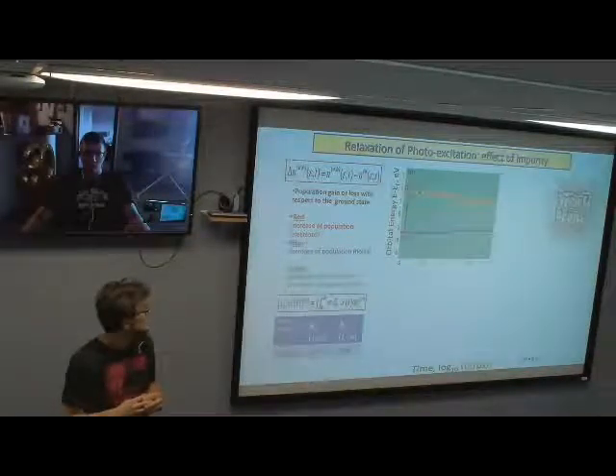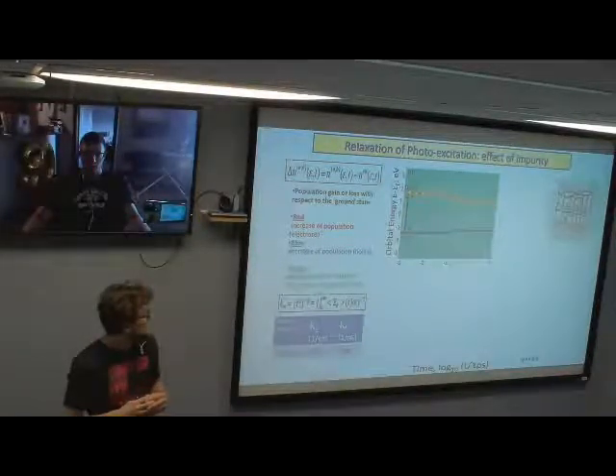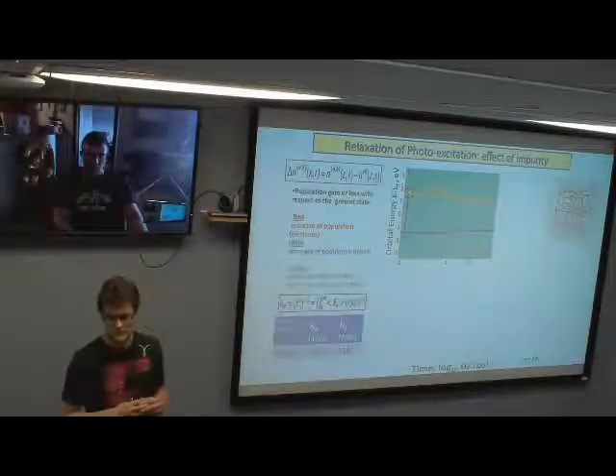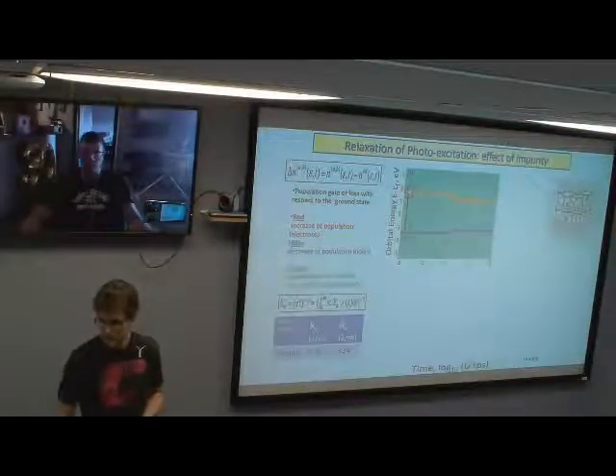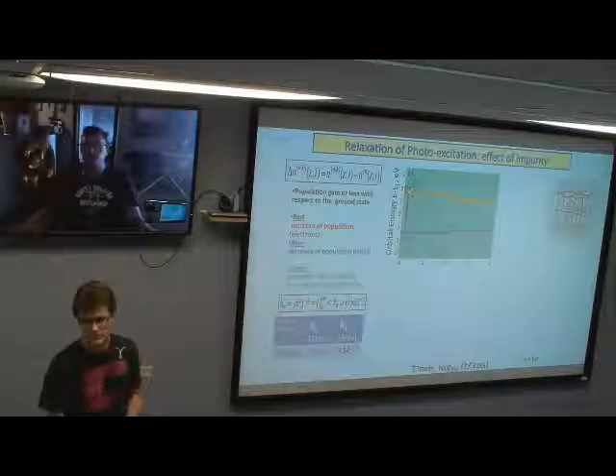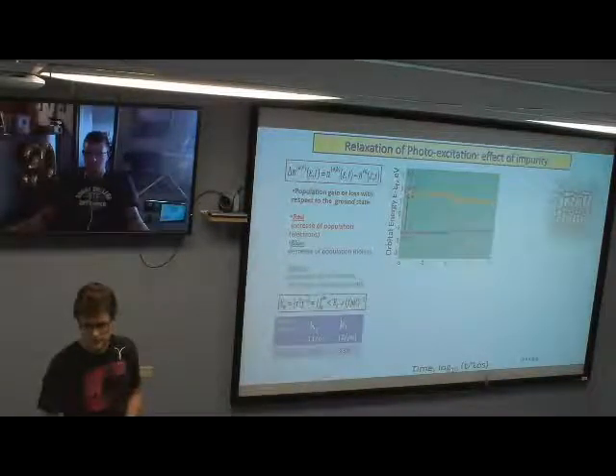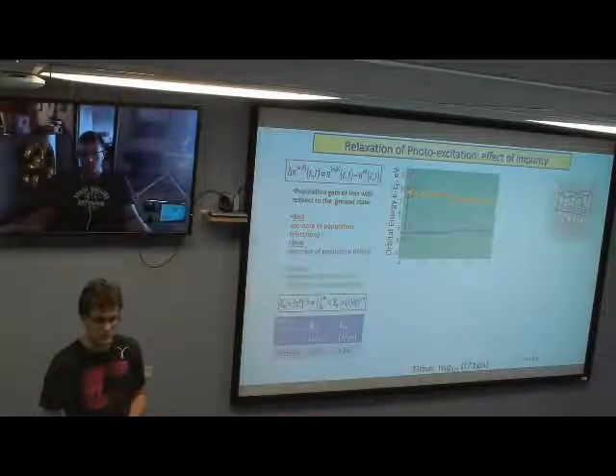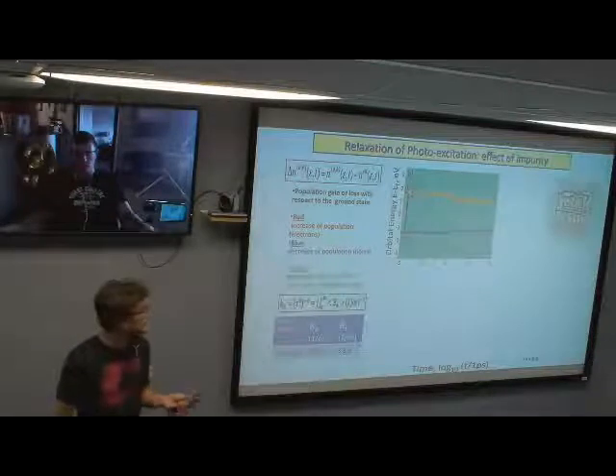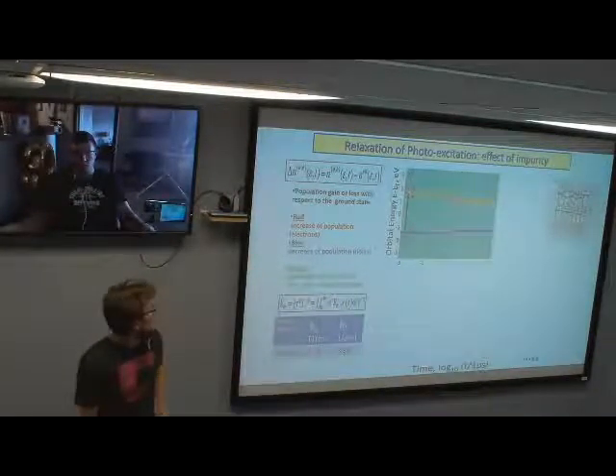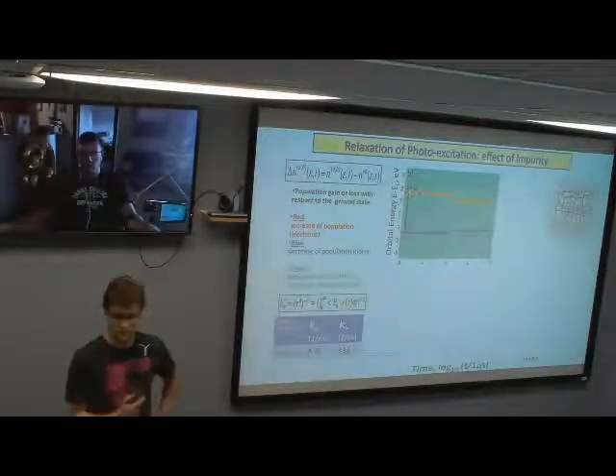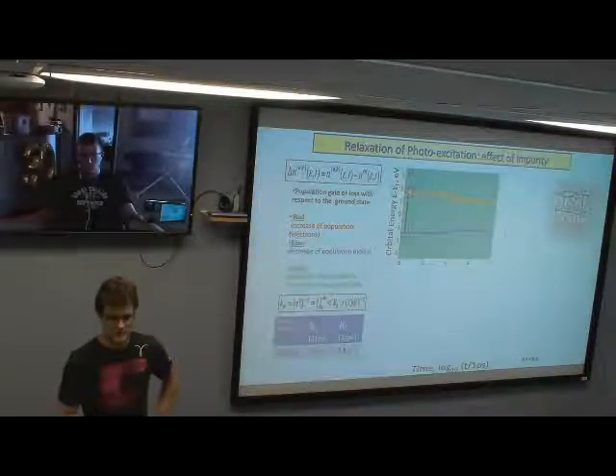And yeah, I'm just not sure. Because of the different surface to volume ratio in the small models, the whole model is almost a surface, and therefore the effect of ligands is stronger and it facilitates more pumping of energy. Yeah, there's more electron density than would physically be there on the surface. Okay. But we're on the right time scale, which is usually a good sign for models of these sizes.